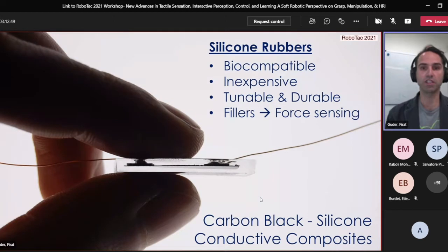So we can easily take the silicone rubbers and add conductive fillers inside to create force sensors. And depending on how much filler we add, we can even produce stretchable conductors and so on. And silicones are very chemically inert. In fact, this is one of the reasons why they are the preferred material for, let's say, breast implants, among various other implants. But when creating devices, chemical inertness becomes a bit of an issue, that's why it's highlighted here, which we will talk about.